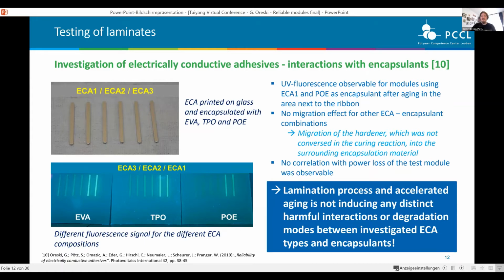We just saw a little bit of hardener migration from the ECA into the encapsulant, but we didn't see any correlation with power loss of the test module. And so our conclusion was actually, yeah, this lamination process and also the accelerated aging is not inducing any harmful interaction between ECA and the types of encapsulants we tested.